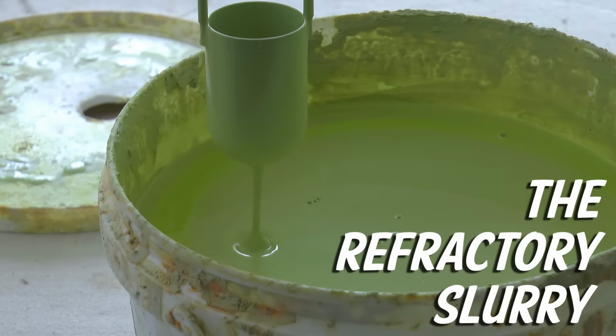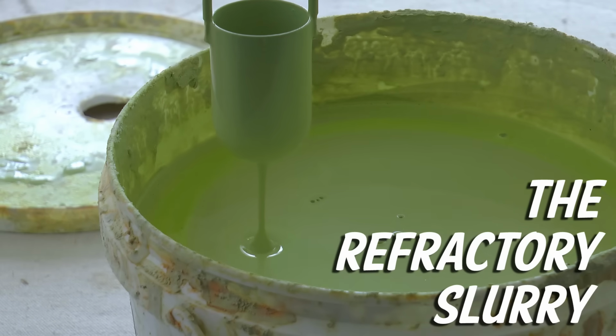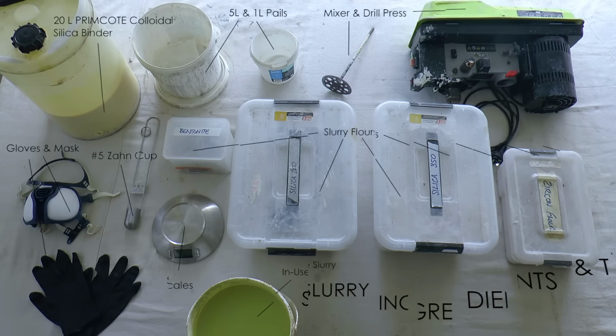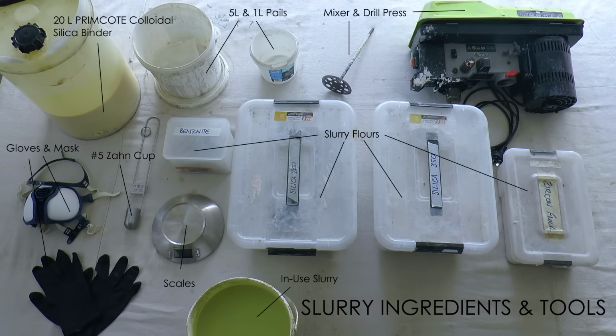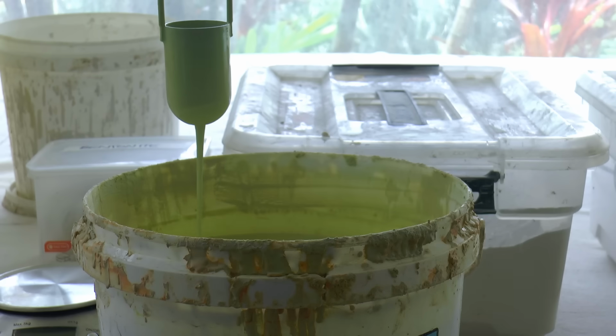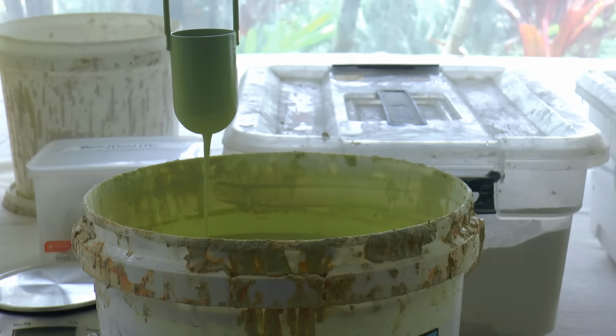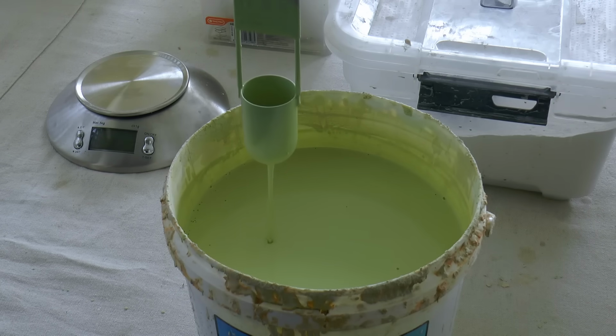Okay, so now that we have a pattern, we need to coat it in refractory material. The ceramic shell process requires a refractory slurry that can be thought of as the binding material that sticks to the pattern and ideally has a consistency similar to warm honey. The slurry both bonds with the pattern and holds the refractory sand in place, allowing layers of ceramic to be gradually accumulated around the pattern and ultimately to form a fully layered mould.